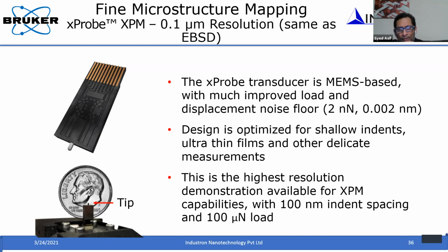This is basically a MEMS-based device where you can apply very small forces, down to nanonewtons, and with that we can apply very small force and very small displacement, so that we can have the spacing reduced between the indents. In this particular case, we were able to reduce to like 100 nanometers between the indents, and then it can map this.